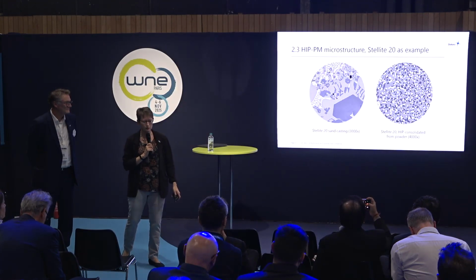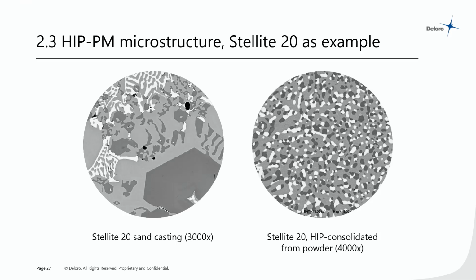And now we get to particularly the DELORO alloys. And what is fascinating about a HIPed component versus a cast component. Now this here, on the left, is a Stellite 20. It's one of our alloys. It's a cobalt, chrome, tungsten alloy with a very high carbon content, a very high carbide content. That is a cast alloy on the left.